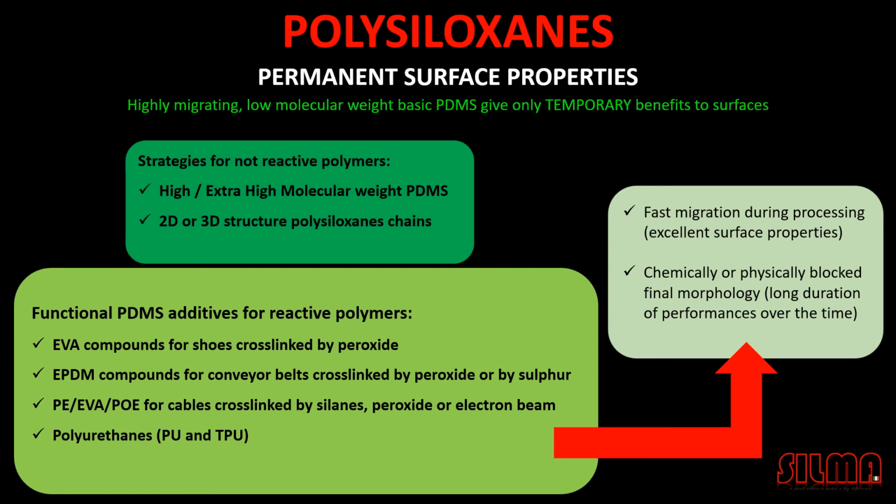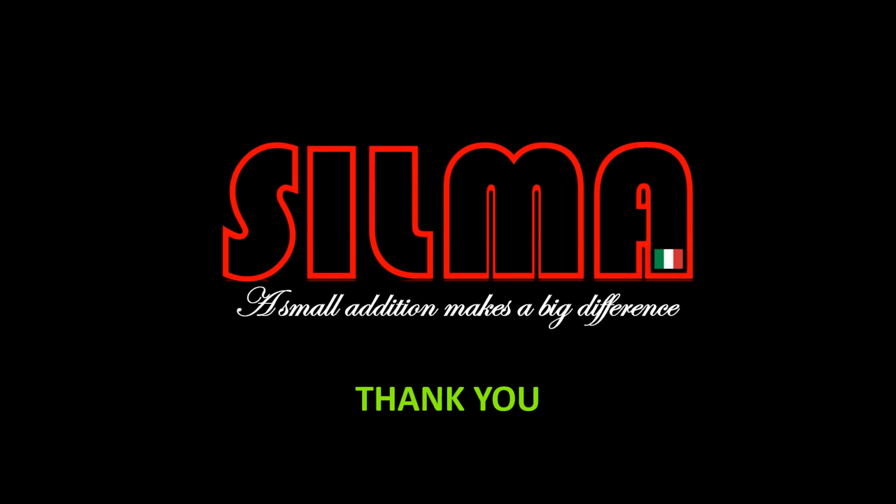Surface properties. It will modify other properties. Sometimes you want the silicone inside, for example, for flexibility at low temperature, or for flame retardancy, or for impact strength. Sometimes you want the silicone to stay inside, but for purely surface properties, the maximum is 100% of the silicone additive going to the surface. So we need to study the way to allow the material to go to the surface as much as possible to reduce the dosage of our additive.